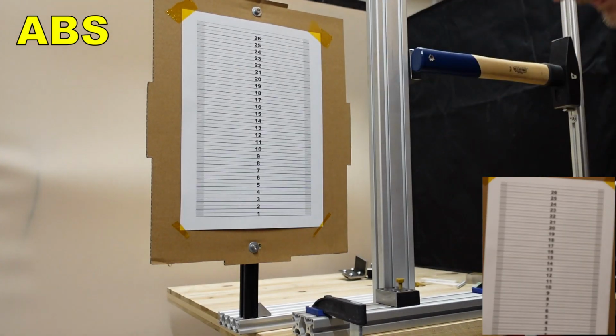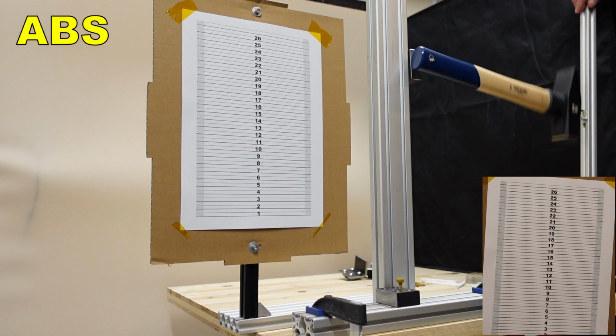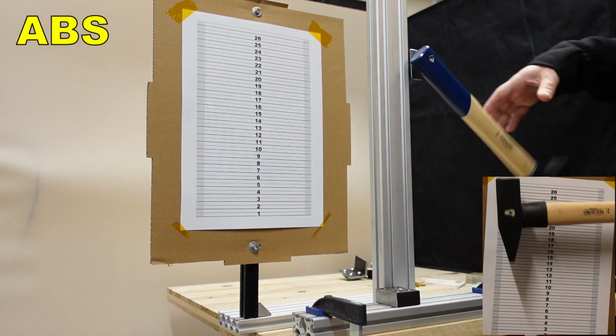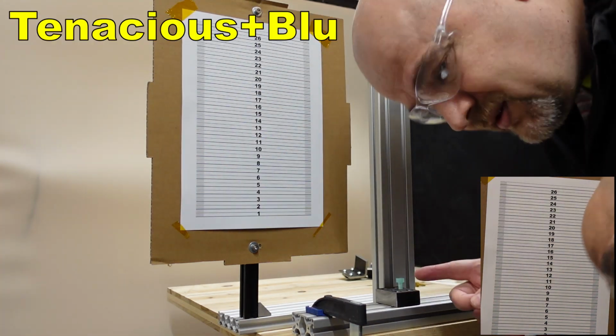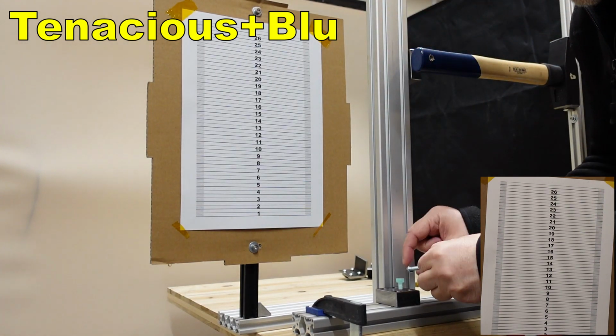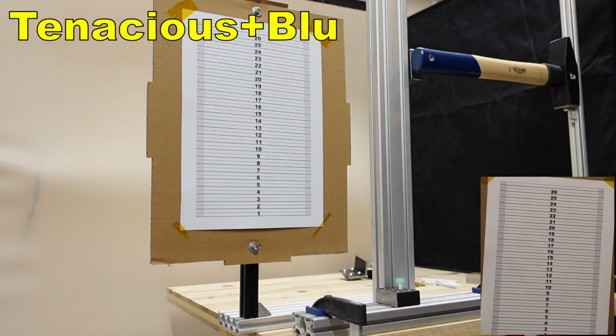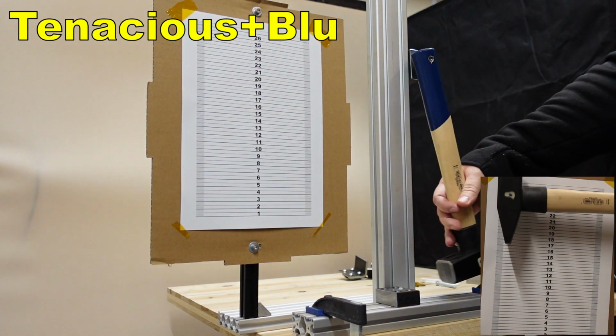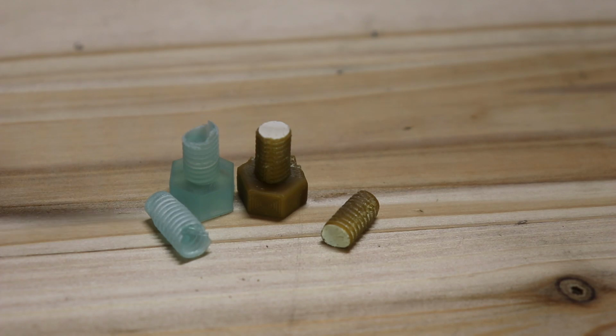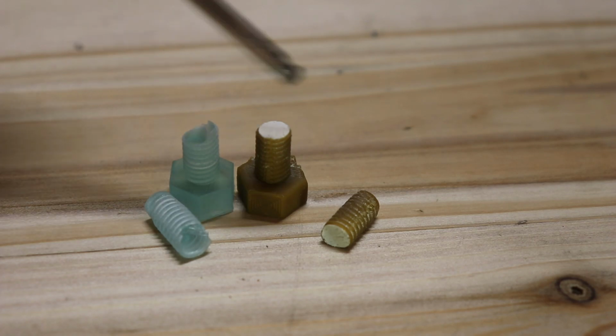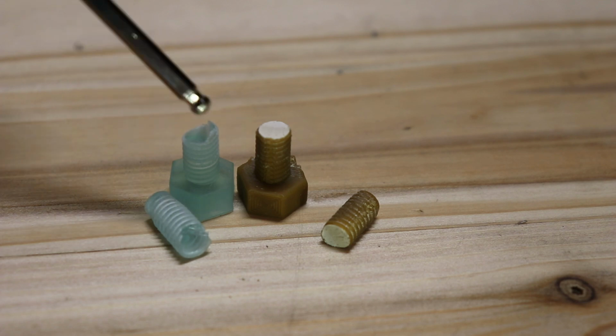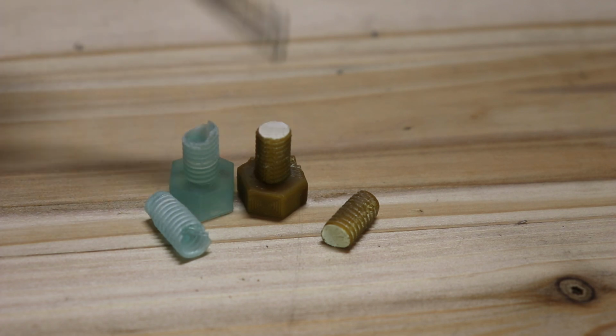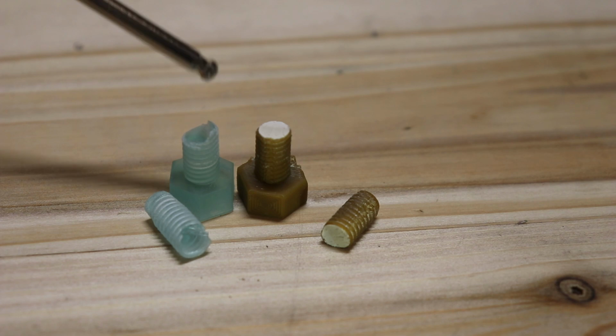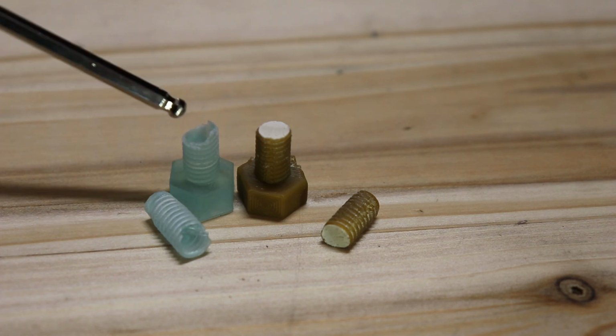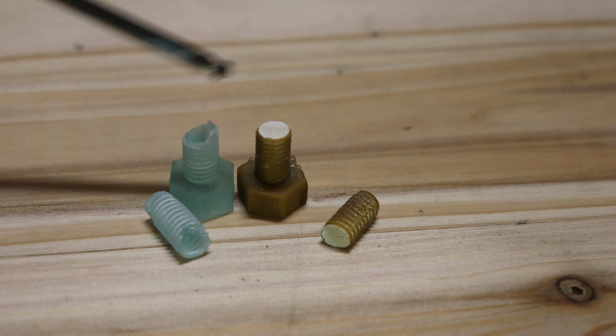This is the ABS. And this is resin, standing out exactly 10 millimeters. And this is the result of the break test. Unfortunately, I have only one test specimen for this test from the resin, so I'm using only one from the ABS. And they broke very similarly, in the same position where they stand out from the testing plate.